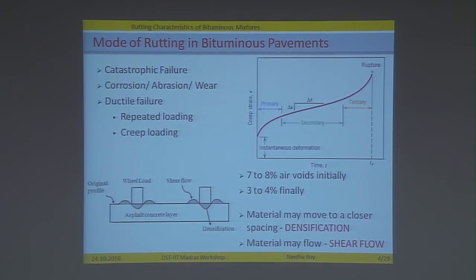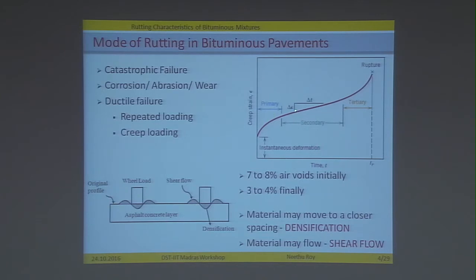This kind of behavior that happens in the material essentially follows a three-stage creep response. Initially, when the air voids are high, it will have a creep response or deformation at a decreasing rate. Then this rate goes to a constant value, and eventually it will start deforming at an increasing rate. This response is called a three-stage creep response.